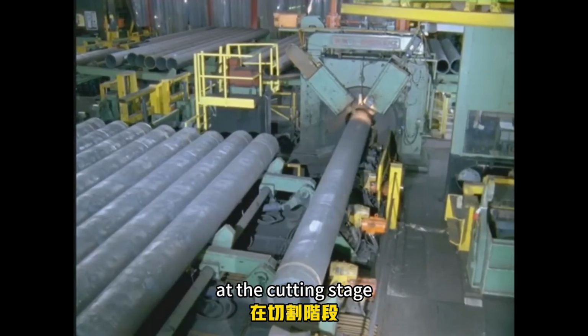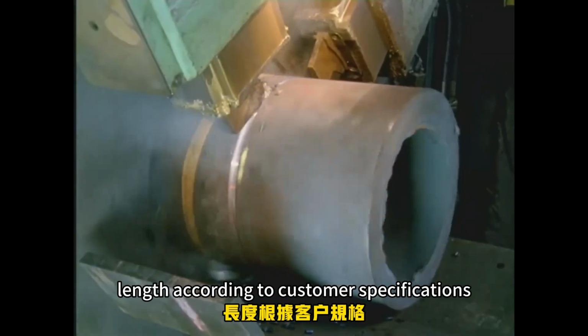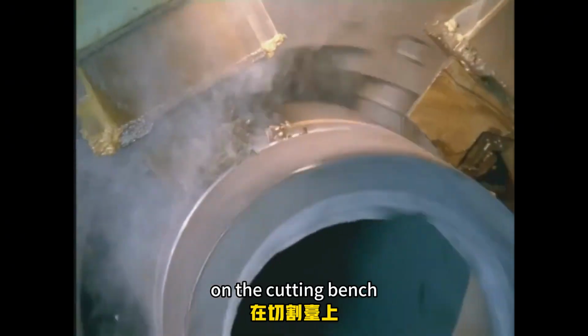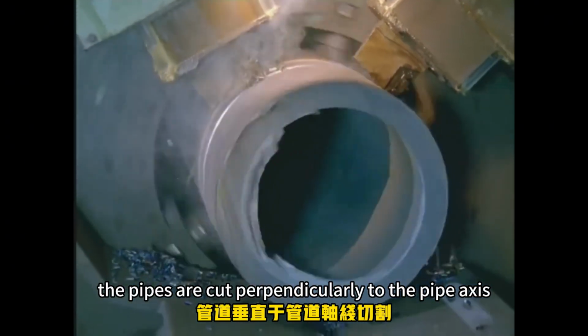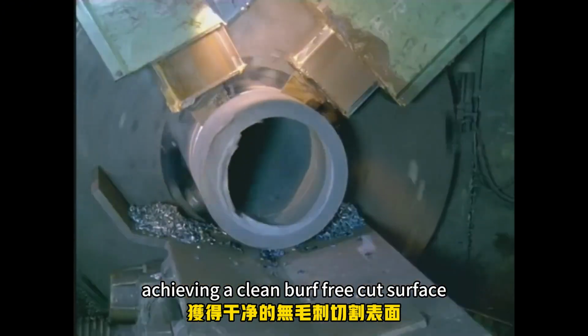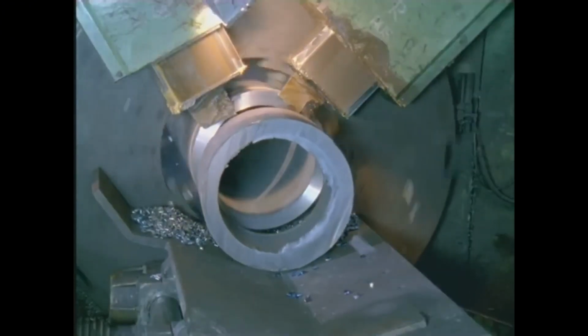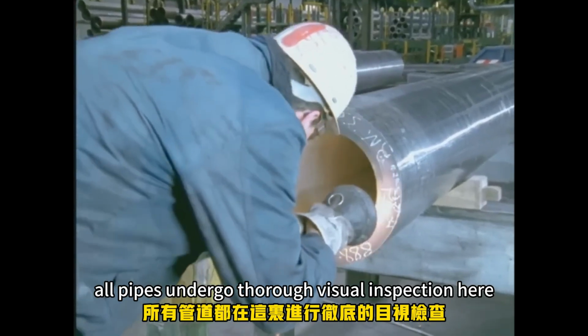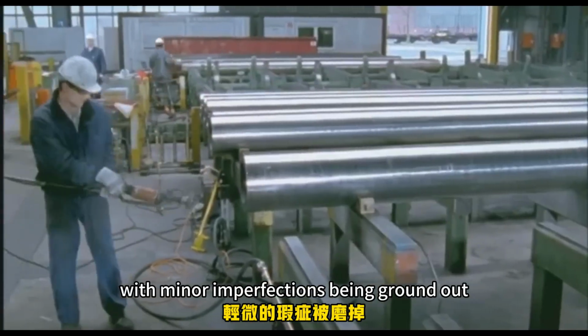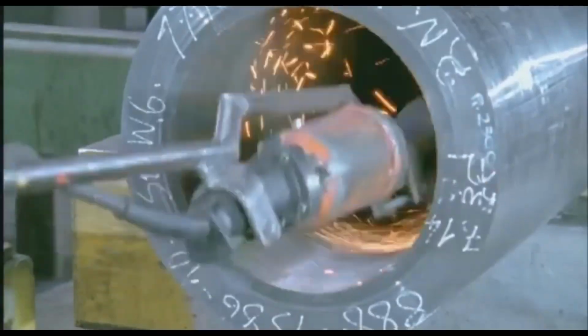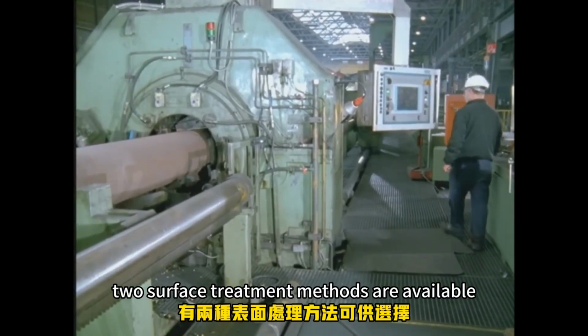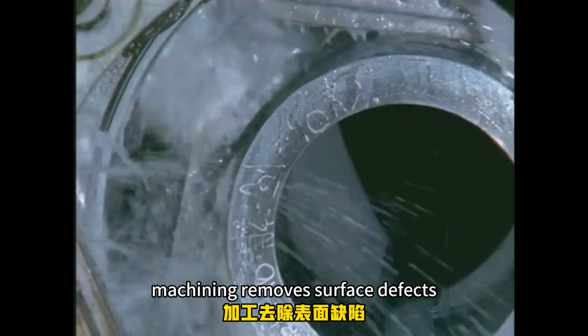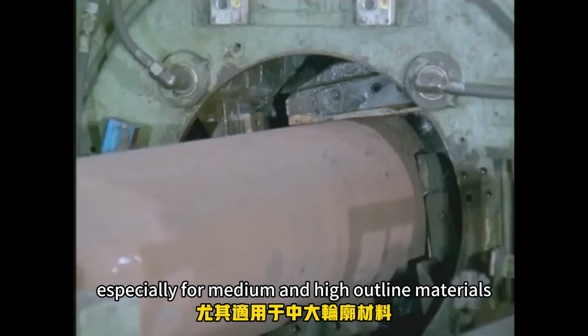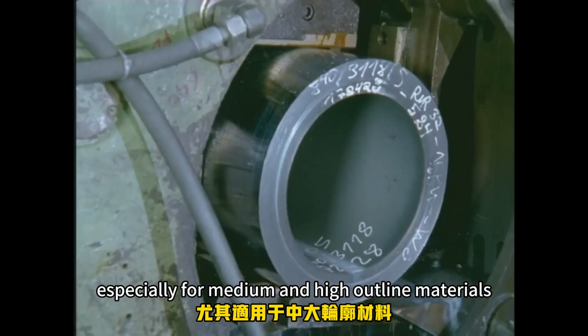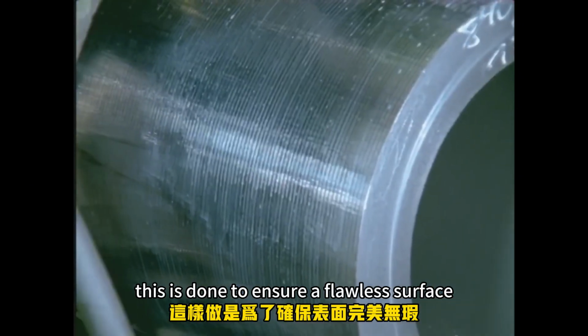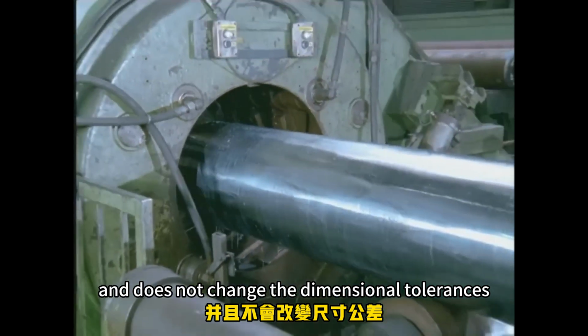At the cutting stage, pipes are cut to the desired length according to customer specifications. On the cutting bench, the pipes are cut perpendicularly to the pipe axis, achieving a clean, burr-free cut surface. All pipes undergo thorough visual inspection here, with minor imperfections being ground out. Here, 2 surface treatment methods are available. Machining removes surface defects, especially for medium and high alloy materials. This is done to ensure a flawless surface and does not change the dimensional tolerances.